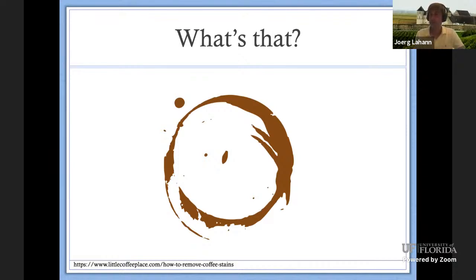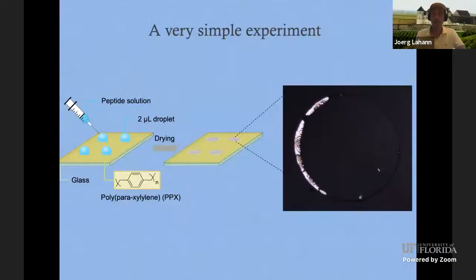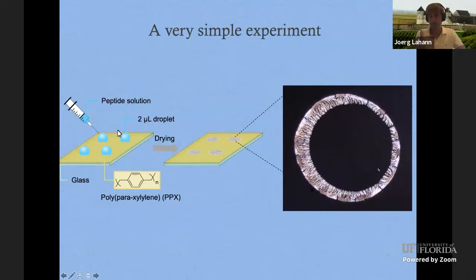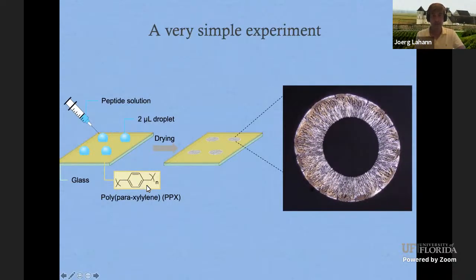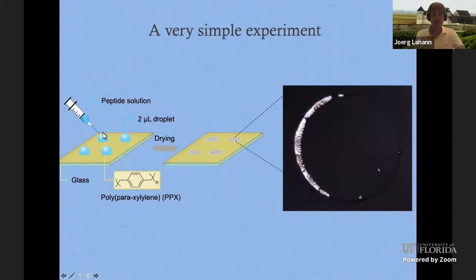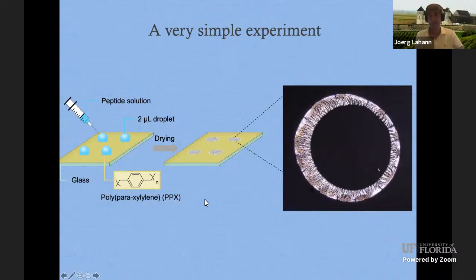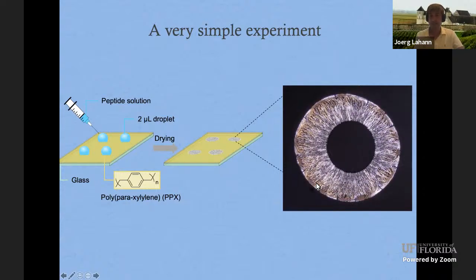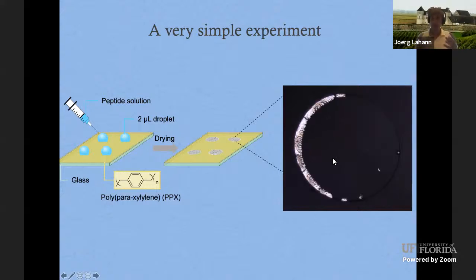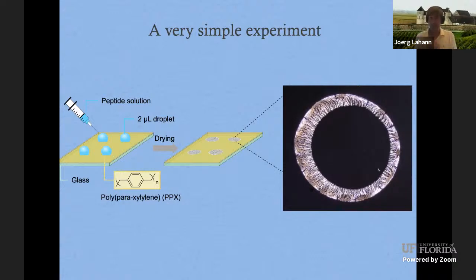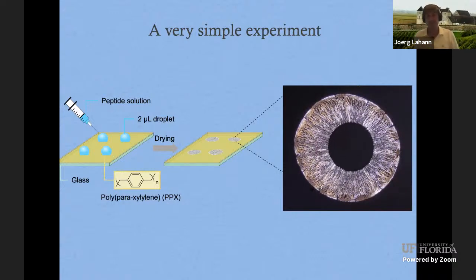So the one thing we can do is we can make very well-defined surfaces. So let's see what happens if we do the following experiment. We're going to take a few droplets similar to the coffee stain. We take the surface that is very well-defined through our CVD process, but we add in this droplet a little bit of a protein or a peptide as well. And so now you basically complicate the process because you also get protein crystallization here. And so you end up essentially with droplets that really look like this system here, okay? So it's much more heterogeneous. In fact, the patterns are relatively complex, and I find them just very intriguing as well.